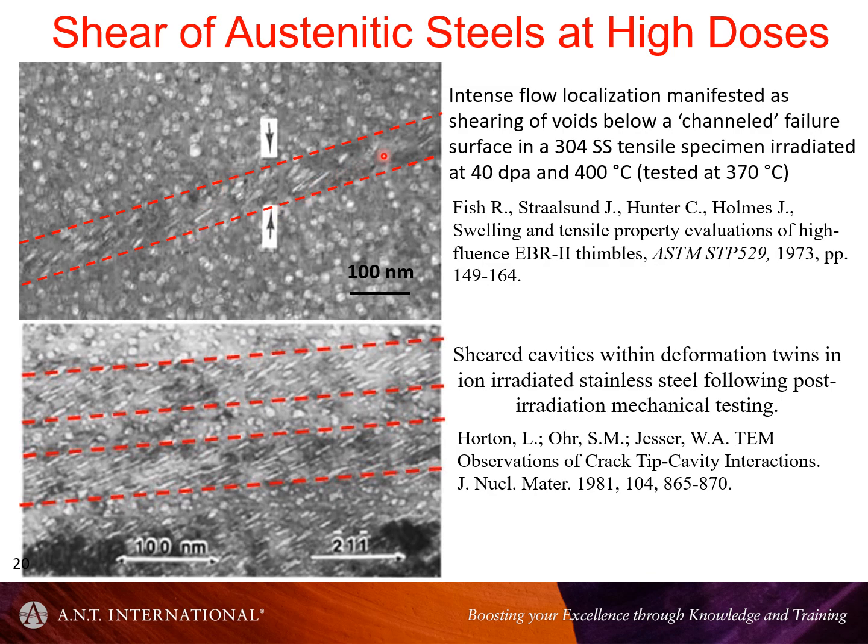So basically, they surmised that perhaps these things coalesce and create a sharp crack. Yeah, I don't know, no evidence for it, and it was assumed that these channels were dislocation channels. So not only do you have a situation where this is a bulk shear, it then gets conflated with the planar shear of many dislocations all on one plane that would have to precede the actual creation of an overlap of cavities from shearing of dislocations on one slip plane.